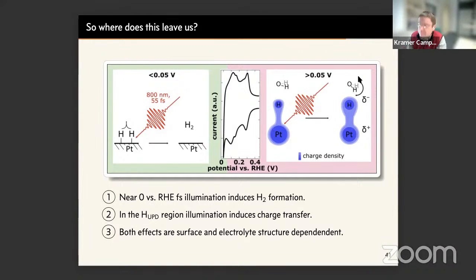If you want to gain some extra momentum in the optical experiment, you have to be a little bit creative about the sample geometry. You have to use a so-called Otto geometry, where you use some kind of near field, where you bring, say, a grating or a prism very close to the electrode surface, which gives you extra momentum in the plane of the surface. You would need to do something like this to gain any kind of momentum resolution, for either electronically or vibrationally resonant experiments. So it's pretty complicated, at least.